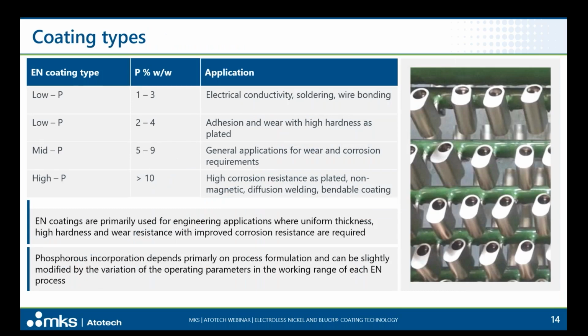Depending on the phosphorus incorporation, we have different electroless nickel coating types with different applications. For the low P electroless nickel processes, we have a phosphorus incorporation of 1 to 3 or 2 to 4, and therefore we can use these coatings for different applications like electrical conductivity, soldering, or adhesion and wear with very high hardness as plated. In the range of mid P, we have a phosphorus content of 5 to 9, and we use these coatings for general applications. And with a high P electroless nickel with phosphorus content higher than 10, we can achieve the highest corrosion resistance as plated, they are non-magnetic and they are bendable coatings.